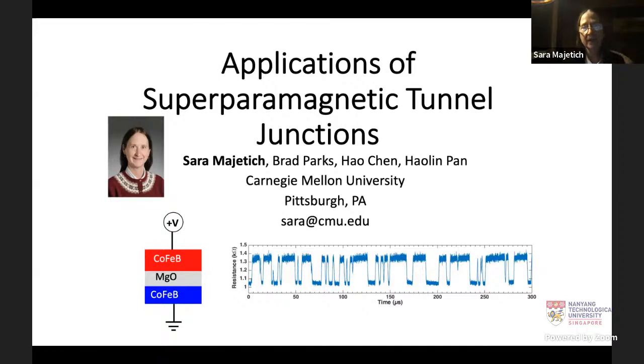So what I want to talk about tonight, well, this morning for you, is a little bit about our work on superparamagnetic tunnel junctions. Everything I'll talk about has two magnetic layers and a tunnel barrier, MgO. Our layers are, in all cases, cobalt iron boron. The difference from a standard tunnel junction is that one of the layers is superparamagnetic, meaning that it is switching spontaneously between perpendicular up and down or to the right and to the left magnetization, depending on whether we have a perpendicular or an in-plane tunnel junction. In either case, the resistance across this tunnel junction is going to vary in time, and there'll be two characteristic levels, and the time that it spends before switching back to the other level is going to vary stochastically.